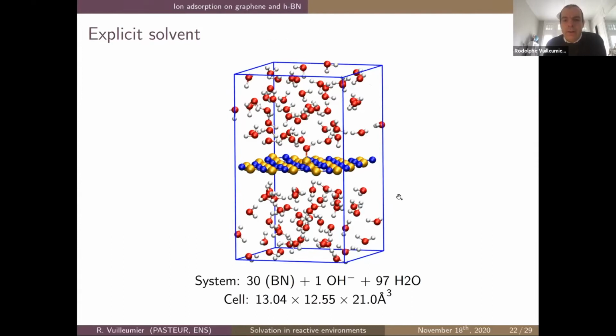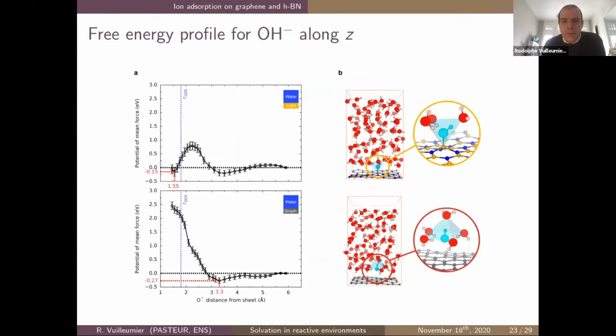And we did, in this case, umbrella sampling simulation that Fabio described earlier, to compute the free energy profile of this system as a function of distance between the OH minus and the surface. Very close to the surface, in the chemisorbed region, we see that indeed BN can chemisorb OH minus, which graphene cannot do. However, we discovered that there was a well a little bit further away, about 3 angstroms, some kind of physisorbed region where OH minus actually has a minimum of free energy and can stay close to the surface without forming a chemical bond with the surface.